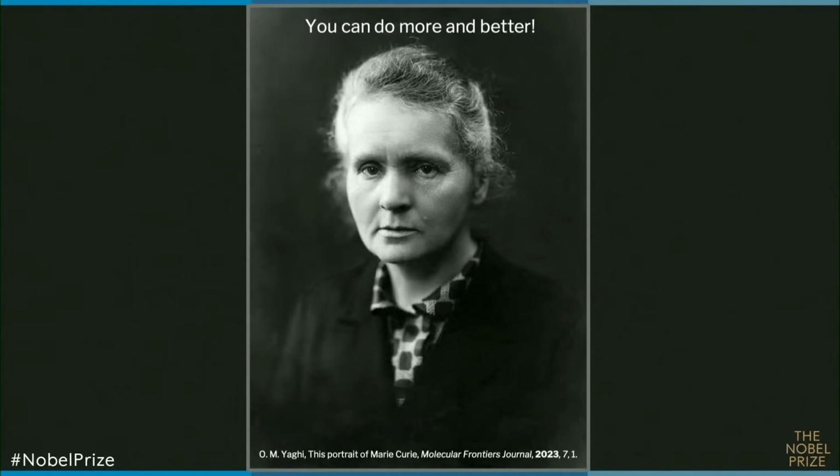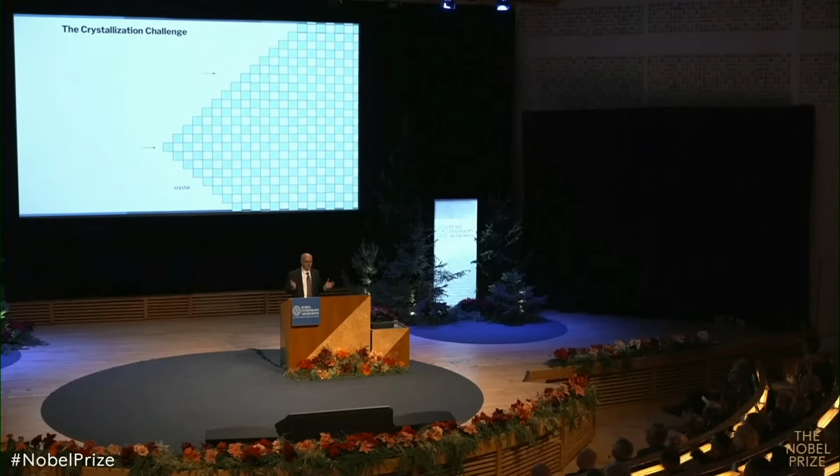So, okay, let's get down to what is the challenge that we needed to solve first and foremost, and that's the crystallization challenge. The crystallization challenge is a challenge where you're taking building blocks and you're stitching them together now through strong bonds, and you need to make sure that on the microscopic level these building blocks can associate and dissociate so that they can correct their positions and make sure that you make an ordered material. If this reversibility is not present, then things will get stuck together and sometimes not at the proper orientation, and they will fall out as amorphous materials or non-crystalline.